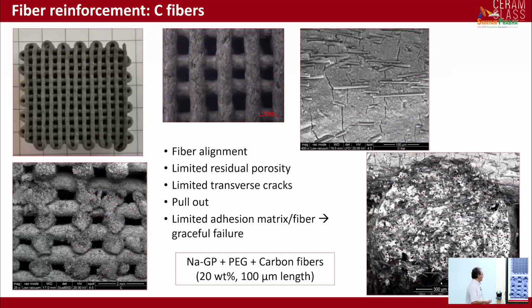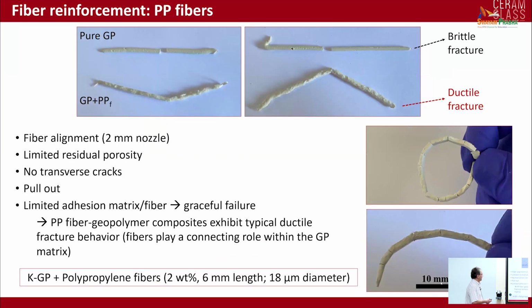We also started trying to make composites, here with carbon fibers, here with polymeric fibers. And polymeric fibers for geopolymers are more interesting because they can allow a degree of ductile fracture that inorganic fibers don't allow. The problem with polypropylene fibers is that they are, of course, commercially available. They're used to reduce the shrinkage, for instance, in mortars, and they can withstand a highly alkaline environment, but their length is quite high. 6 millimeters is the minimum that you can purchase. And this makes it difficult to have a large volume of fibers inside the material. So typically we cannot put more than 2, maximum 3% of these fibers inside the slurry. Otherwise the ink will clog the nozzle.